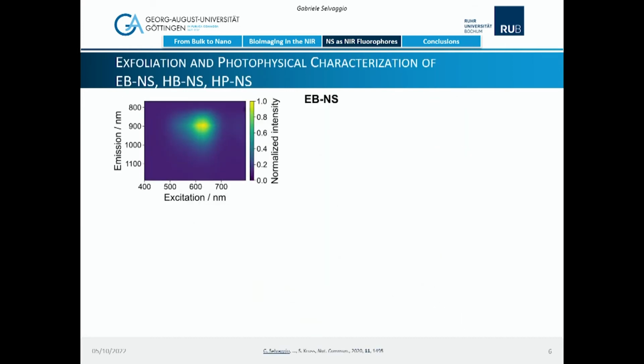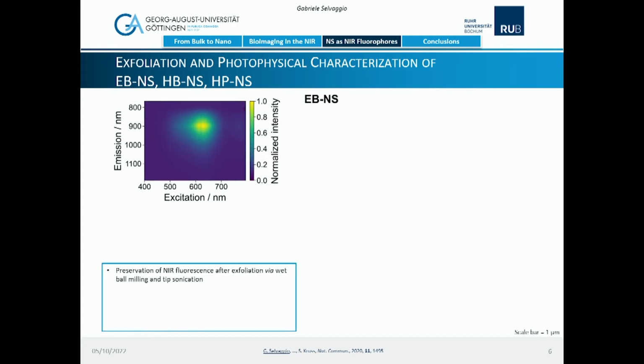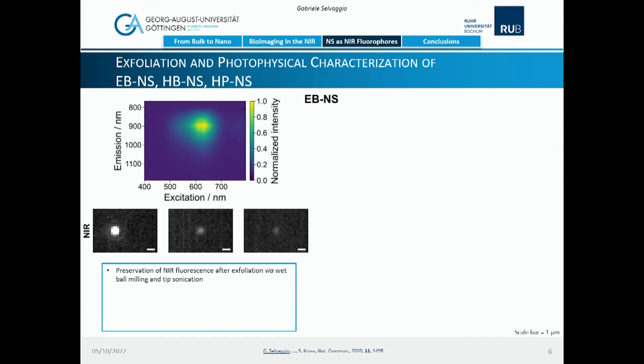We said earlier that after exfoliation, the fluorescence is preserved, as you can see here in this 2D spectrum. But then you might ask yourself, how do these nanosheets really look when you image them in a near-infrared microscope? They look like these fluorescent spots, and if you keep in mind the scale bar, you might notice that these are in most cases resolution-limited spots. And this means that given Abbe's law for the resolution limit, you cannot resolve spots below roughly 500 nanometers.